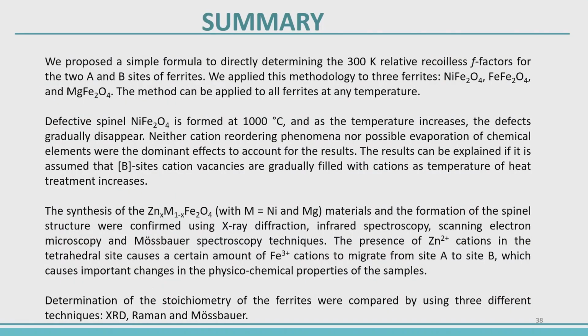So let me summarize because it's time. I just presented in summary three things. First, we propose a simple formula to directly determine this. We did it at 300 K, but this can be done at any single temperature. There is no necessity to do the temperature dependence of the isomer shift or absolute area. Just one single temperature, and we derived some formulas to determine the relative recoil-free fraction for two sites, not only one, as assumed when we use this method.